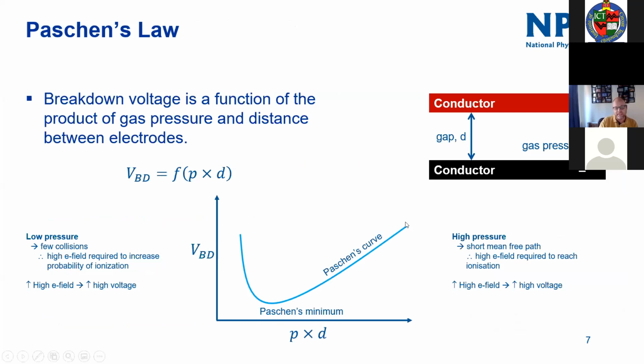The breakdown voltage in a gas is dependent on Paschen's law, which effectively, for the purposes of what we understand here, is that as you reduce the pressure of that gas, the breakdown voltage drops until you get to a minima, and then it starts to increase again. So it just happens that for the sorts of gases that we're normally used to dealing with in the atmosphere, this Paschen's minima is somewhere up at cruising altitude of aircraft. And so this is why the aerospace industry is particularly interested in this partial discharge phenomenon, because if it follows Paschen's law to any degree, they are going to see partial discharge voltages, or the inception voltages for those partial discharge, dropping as they climb in altitude.